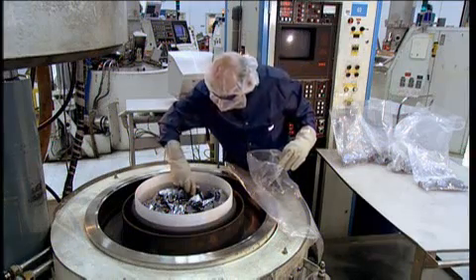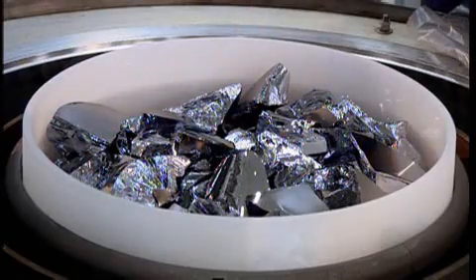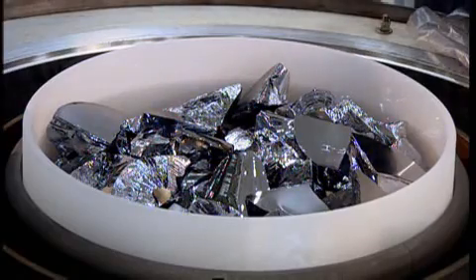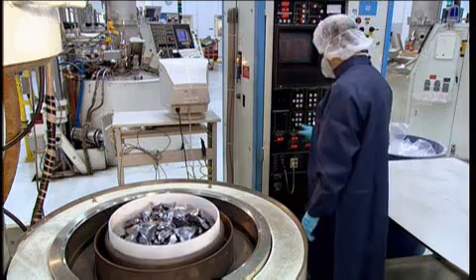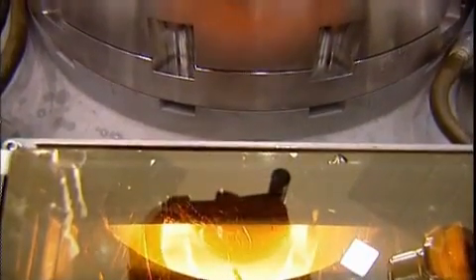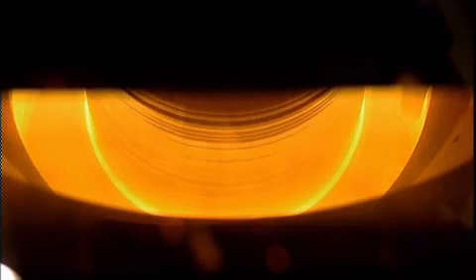It took decades to discover a way to produce silicon with a perfect monocrystalline structure. They begin with raw polysilicon, or poly, and heat it to 1420 degrees Celsius inside a special sealed furnace, which has been purged with argon gas to eliminate any air. The resulting lake of molten silicon is then spun in a crucible, and a silicon seed crystal, roughly the size and shape of a pencil, is lowered into it while spinning in the opposite direction. As the molten polysilicon is allowed to cool, the seed crystal is slowly withdrawn at around 1.5 millimeters a minute.